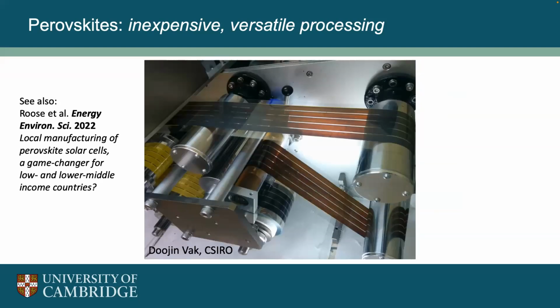Because they can be processed at low temperature, it opens up manufacturing on different substrates, and this is actually an example. Instead of manufacturing on glass, for example, or on other substrates, this is on a plastic foil, and you can also do this on metal foils as well. This is a roll-to-roll printer, where this is the precursor solution, a precursor film here, and then it's heated to form this crystalline film. And so this opens up really high throughput manufacturing. You can think about roll-to-roll newsprinters essentially making solar cells, which is really exciting and, again, a very big paradigm shift from what we can do with silicon cells.